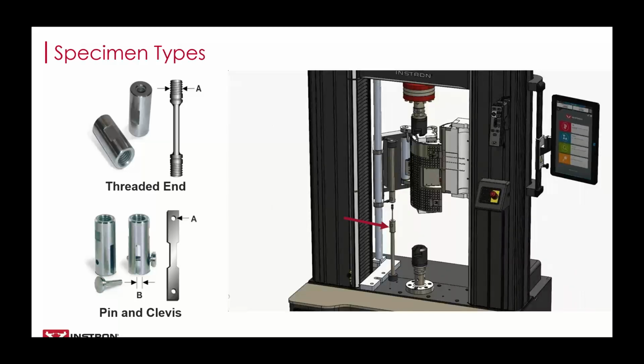On the specimen, you can see a slot machined for the pin. This is labeled as callout A. And on the holder next to that specimen, you'll see callout B, which corresponds to the thickness of the specimen. The ratio of A to B here is very important. To get a more reliable connection and minimize the chance of misalignment, we always recommend that you use a pin that is equal to or greater than the thickness of your specimen.